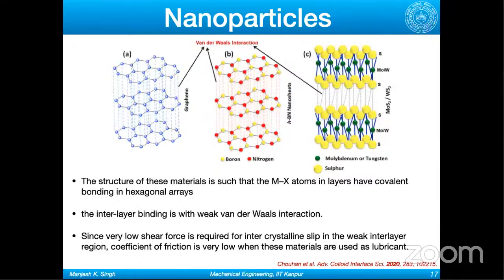These are some typical examples of nanoparticles which are normally used as solid lubricant, or many times used as solid lubricant. All of these, like graphene, MoS2, WS2, or hBN nanosheets, have a layered structure. Within the layer, they have covalent bonds, and between the layers, they have weak van der Waals interactions. So when you apply normal load,